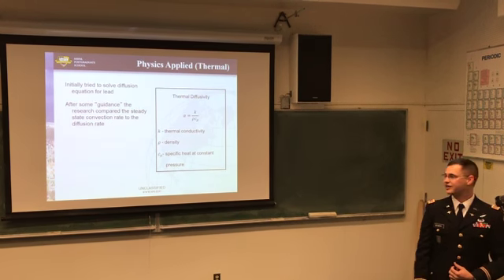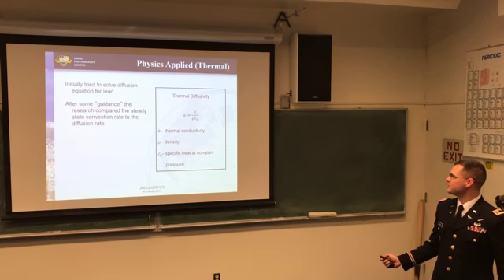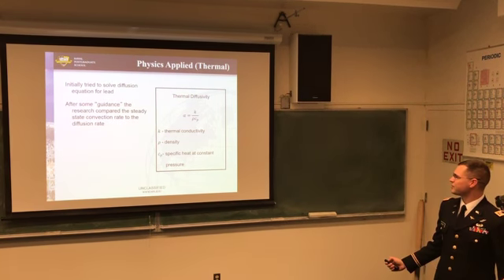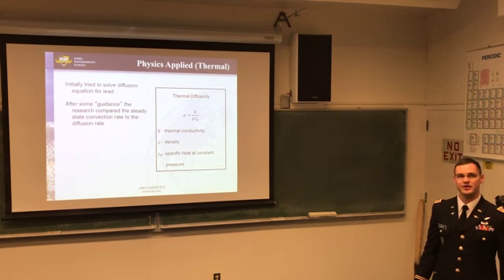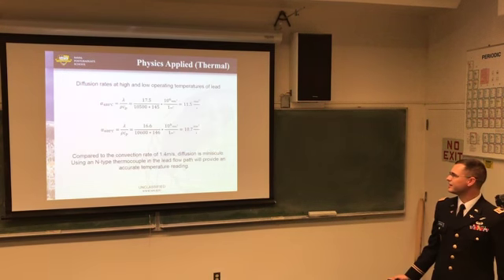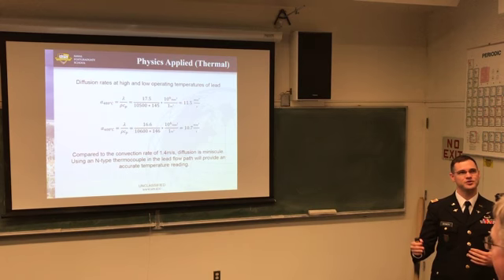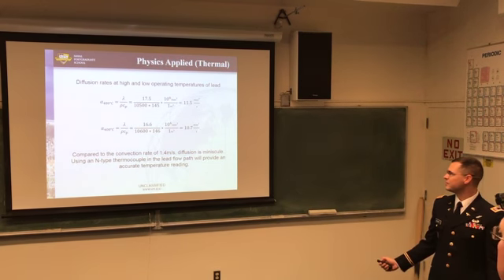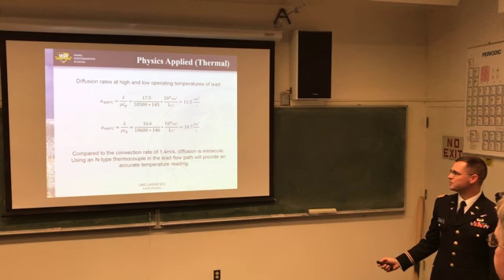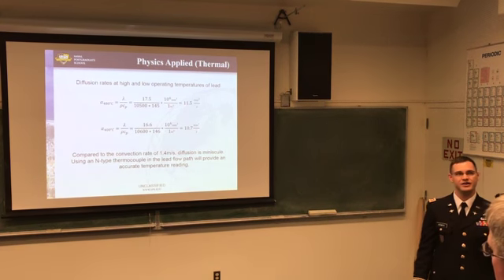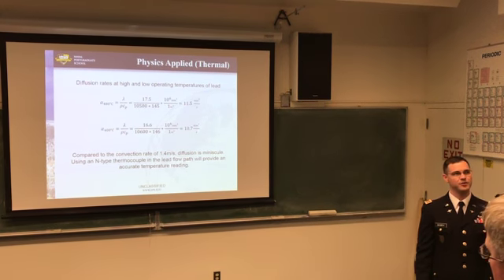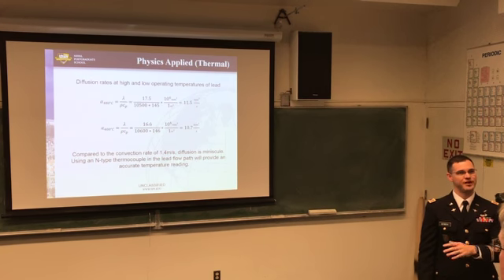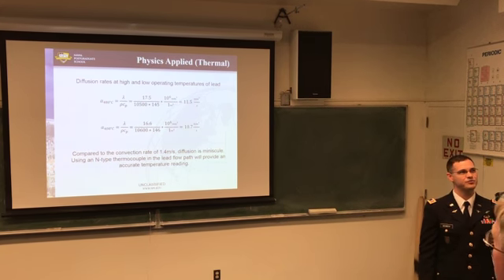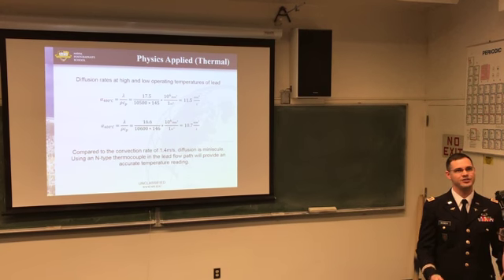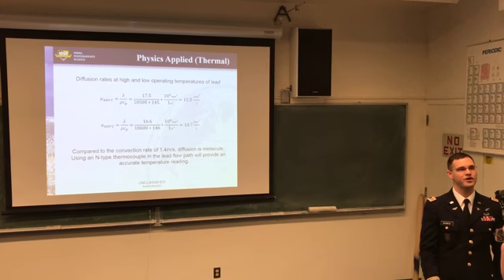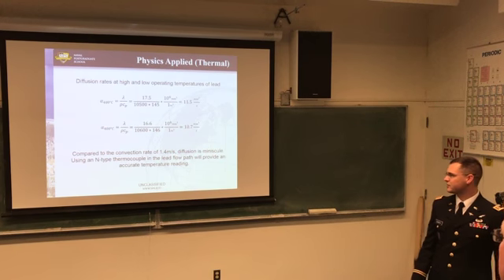convection rate. And so we looked at the thermal diffusivity of the reactor, which is dependent on the conductivity, density, and the specific heat at constant pressure. And then solved that for the upper and lower temperatures within the lead-cooled fast reactor to get a very minuscule amount of diffusion in comparison to the convection rate. So that tells us that with the thermocouples that are possible by material science, by putting those in the direction of the lead flow path, you can get both a temperature distribution and the lead flow pattern across the reactor. And it makes it much more simple.